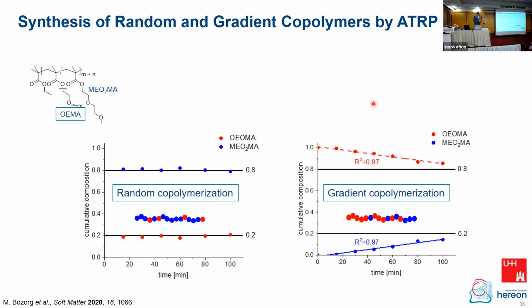And here in this case, Mariam Bosok, who did that work in her PhD, made a copolymer of 2 different monomers, one having a diethylene glycol side group and another one which has an oligoethylene oxide side group. Oligo, it's a distribution. Mainly these are 8 ethylene oxide units, but it can also be a little bit less and a little bit more. So it's an industrial product. Okay. And so depending on the copolymerization of these two monomers, they are also nicely statistical copolymerization. You can adjust the LCST at higher temperatures than what I have shown before.